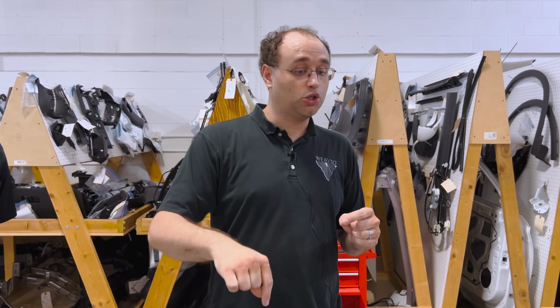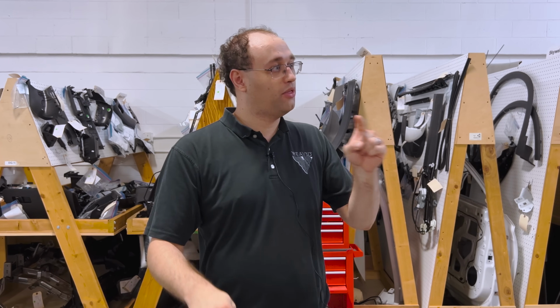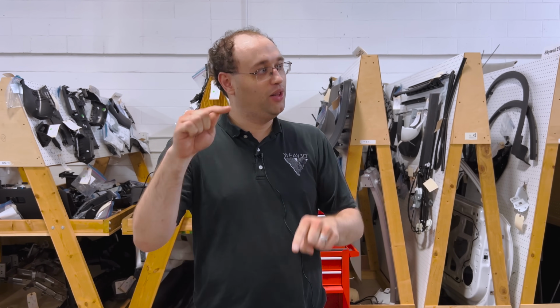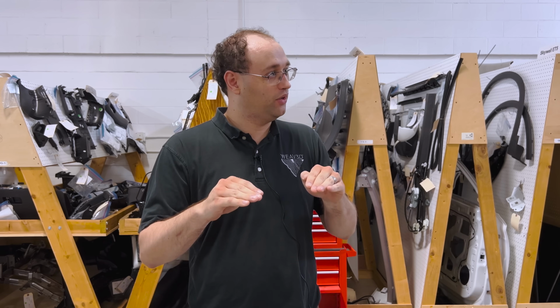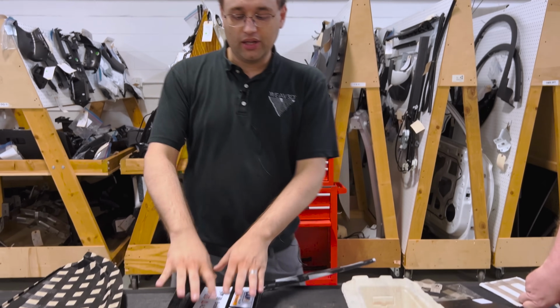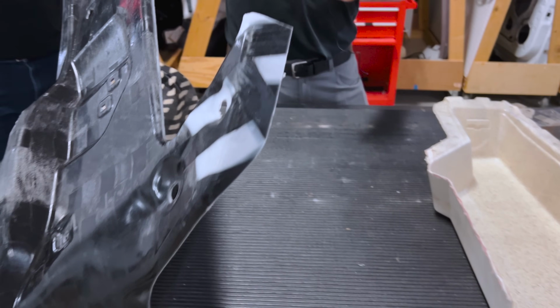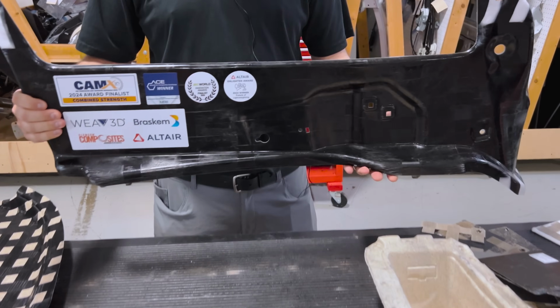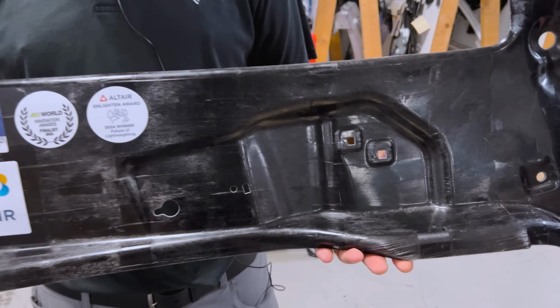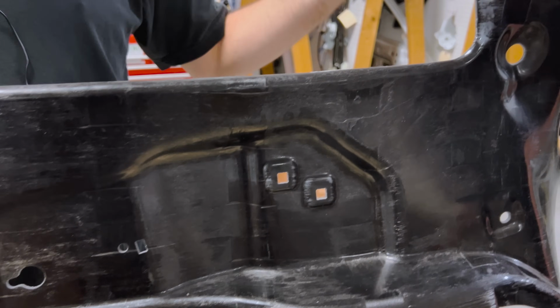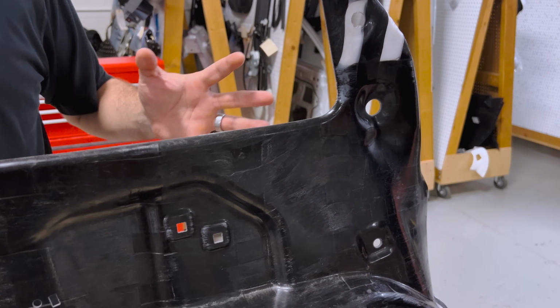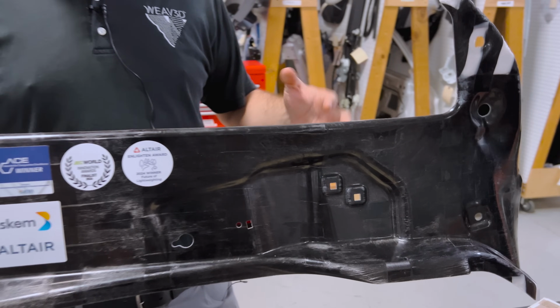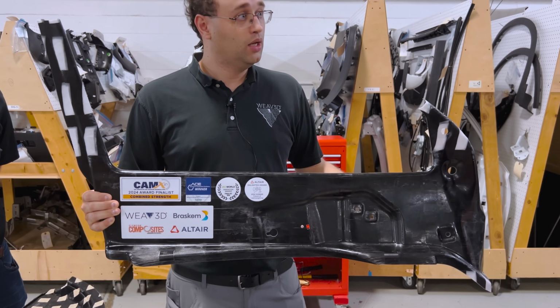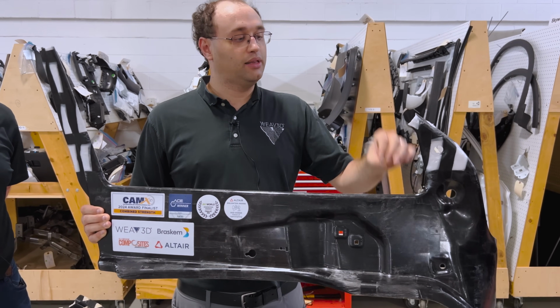So what we've found in our experiments and some of the applications that we've tested is you can actually control whether the fiber breaks first or whether the polymer starts to break first, depending on the relative ratios and the relative stiffnesses of the two materials. So that kind of brings me into this part. This part is actually an automotive door structure. It was designed by Clemson University in partnership with Honda as a way to replace a steel door assembly. They went to a carbon fiber nylon organo sheet, and then we were asked to come in and redesign the organo sheet into polypropylene. So the way that we came up with this design is it's actually a sandwich structure.